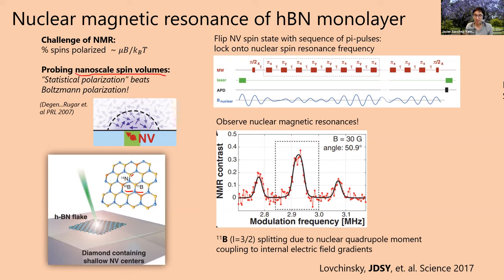But what's really cool, if you have a nanoscale magnetic sensor, is that if you go to the nanoscale and you're probing a really small volume of spins, the spins are not going to all cancel out, because you have a small population and there's always going to be some net little spin polarization. We can call it a statistical polarization, and that goes as square root N, where N is the number of spins you have. As you shrink down the volume of spins, the net fractional statistical polarization grows in size, to the point where you always have some amount of net polarized spins and you can detect those.